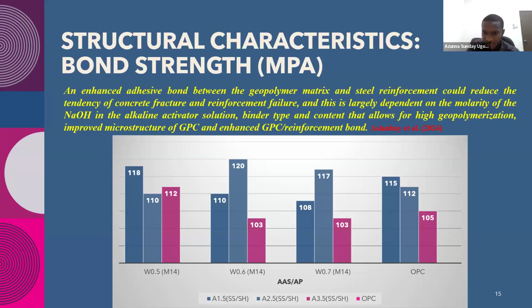The highest for normal concrete is 115. What this is saying is that when a structural element fails, there's a fracture between the concrete and the reinforcement. The bond between the concrete and the reinforcement is what we call the bond strength. What this implies is that a geopolymer structural element can absorb more stress before the reinforcement and the concrete split, more than normal concrete.